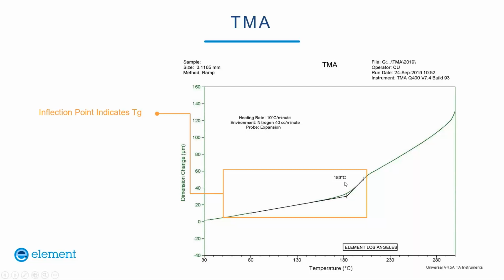It's also worth noting that sometimes glass transition temperatures are well below room temperature. And so if you start your test at 30 degrees C, and the glass transition temperature is down here at 0 or something, you'll miss it. So often we have to start experiments well below room temperature for materials like rubbers and elastomers.